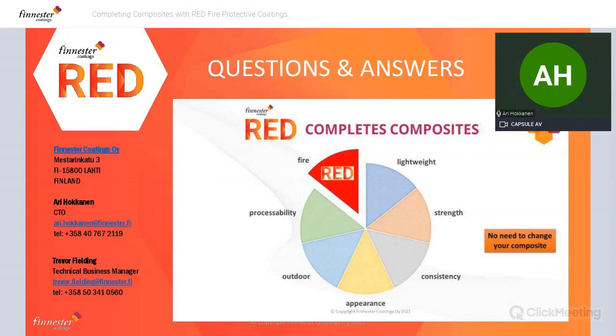Second question here is, how about delamination between the coating and the bulk material for mechanical applications? Is it possible to reduce the influence of the critical interface between them? Well, that comes down to the compatibility and adhesion. When we know the substrate, we'll match our base coat technology to get the best adhesion. So if it's epoxy-based or polyester-based, whatever your substrate is, we'll match, and that's why we need that sample to really test the adhesion before doing anything else. If there's no adhesion, there's no fire protection.